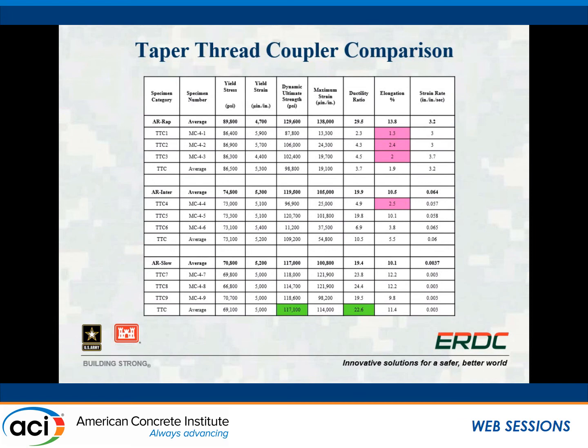And so first with the tapered thread coupler, and you can see that in this case, in the quasi-static strain rates, these couplers perform very well. You get similar tensile strengths and very similar percent elongations. But as soon as the strain rate increases to intermediate and dynamic strain rates, these properties are jeopardized fairly significantly. So we get reductions, and the bold lines here on the top, this is for the as-rolled controls, just for comparison. So you can see when we get to the dynamic loading condition, we reduce our tensile strength, and we also get significant reductions in percent elongation.